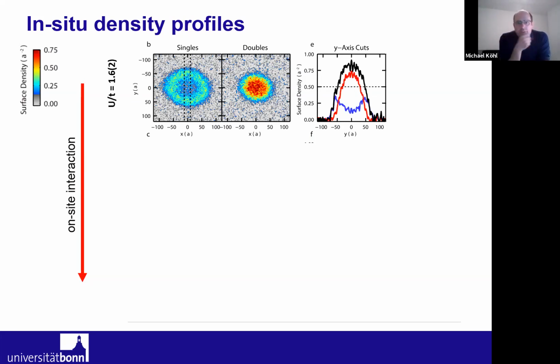And here is sort of the toy model example of the metal to Mott insulator crossover in the singles and doubles. So this is all done in the harmonic trap, these experiments. So we expect to have a higher density of the particles at the center of the trap, a lower density at the edge. And here are the 2 pictures that we take. That's the singles picture. You see that the singly occupied sites, they're at the edge of the trap cloud, and the doubly occupied sites, they're at the center. So in reality, these 2 pictures are of course superimposed. So these doubles fill precisely the hole that the singles have, and we displace them here for clarity.